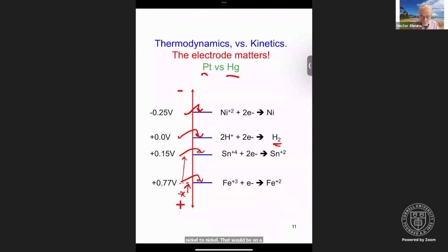If we do the same thing on mercury, if we start here, what's going to happen? Actually, you can't do that one because mercury will dissolve. So this process is out at a mercury electrode. It's just too positive for mercury. So we're now here, and we raise the level. When it gets to this point, we can again carry out the tin 4 for 2 electrons to tin 2. We get to the hydrogen evolution, where on platinum, remember, there was this enormous evolution of gas. At a mercury surface, nothing, and I mean nothing, happens. Why is that? It's that the kinetics of hydrogen evolution at mercury are horrendously slow. And so even though thermodynamically you should be evolving hydrogen, kinetically it's just too big a barrier to overcome.